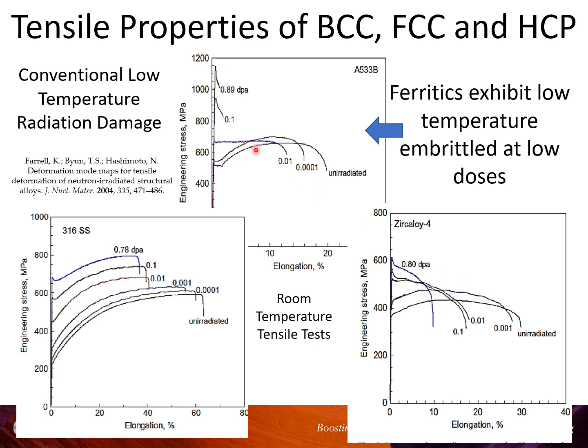Now, in the ferritics, it's not so much of a load drop, because even in the unirradiated state, you have this region of Luder's band formation, which is typically from twinning, I think, or strain aging. Well, it can't be strain aging in this case. It's a room temperature test, but I'm not going to talk about that because we're not going to talk about ferritics. The reason this is on here is just to illustrate how irradiation, even low dose irradiation, severely embrittles the material. So although it increases the hardness immensely, there's a very severe embrittlement associated with that.